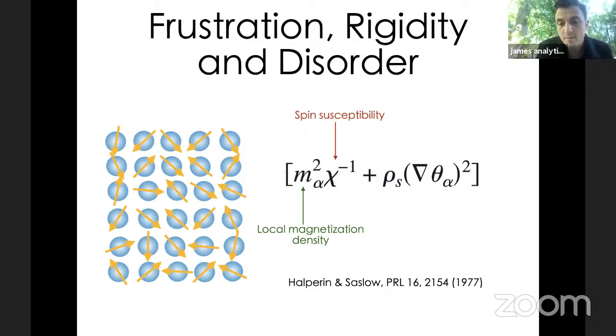And this was described in a paper by Halperin and Saslow, where they studied the free energy associated with this kind of collective motion. And they divided the free energy into two main components, one of them to do with the local magnetization density around a certain region. That's what basically alpha corresponds to, and obviously dependent on the magnetic susceptibility of the system. And then the other energetic term is, of course, the stiffness of these spins and what their local rotation angle actually is.